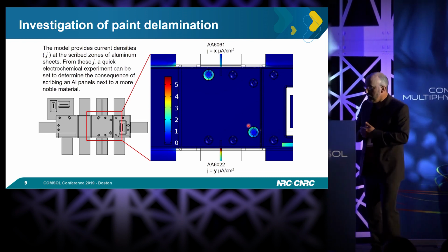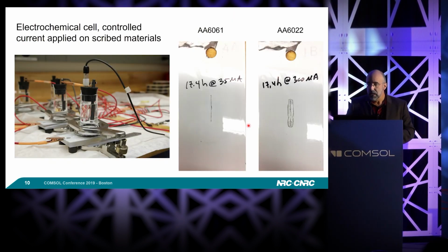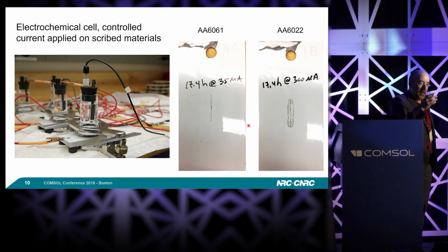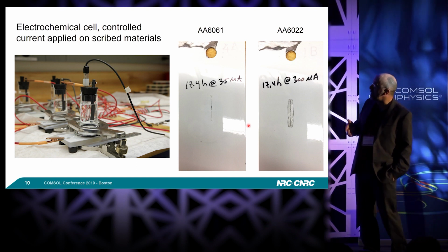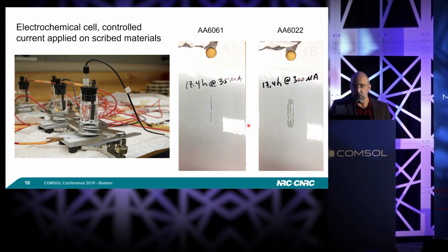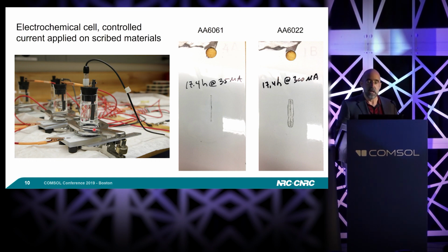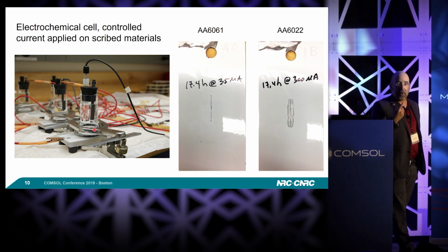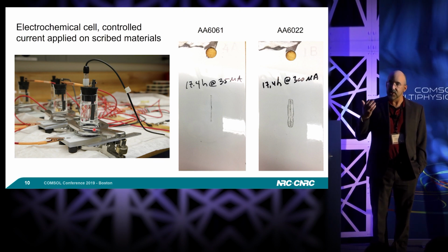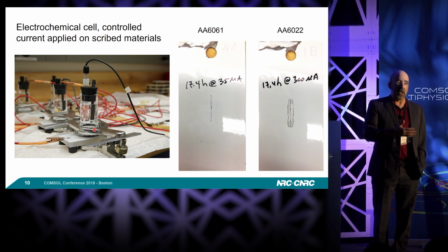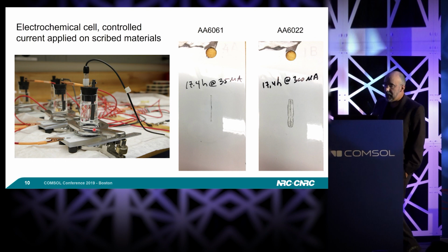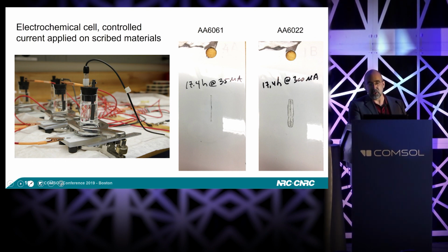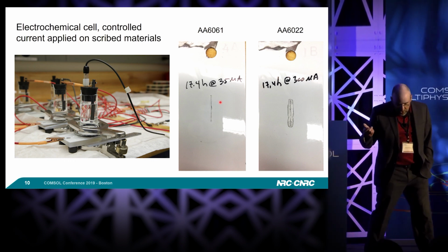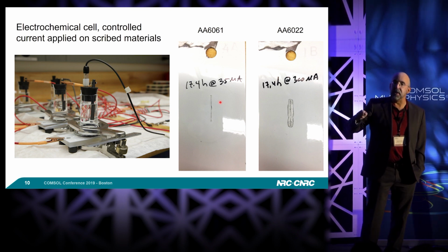I don't know. So we went to the lab, and then we scribed the two corresponding materials. We put an electrochemical cell on them, and then we applied the current density that the model provided us with. And then overnight, 17.4 hours simply because we did it overnight, the day after, we took a knife and tried to peel the paint.